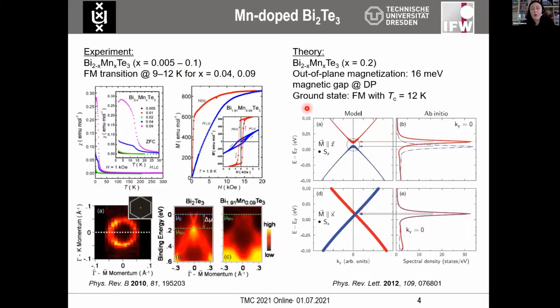So these low expectations for extrinsic manganese doping were further substantiated also by theory that looked at this modeled compound, so manganese taking up some crystallographic positions of bismuth in the structure of bismuth telluride. They calculated that indeed this configuration should show a ferromagnetic ground state, but the resultant magnetic gap at the Dirac point would have been very, very small, so not substantially large to provide robust quantum anomalous Hall effect.